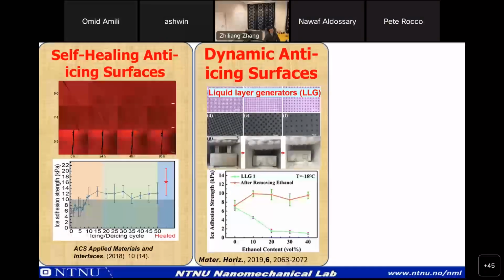You know, most of the anti-icing surfaces, they are of static nature. So we, for the first time, introduced dynamic anti-icing surfaces. That means the interface is not static. Interface will change with time. So this dynamic anti-icing surfaces will have very low ice adhesion. Also, you see there is evolution in the interface between ice and solid. So this is a kind of a new concept in the smart icephobicity.